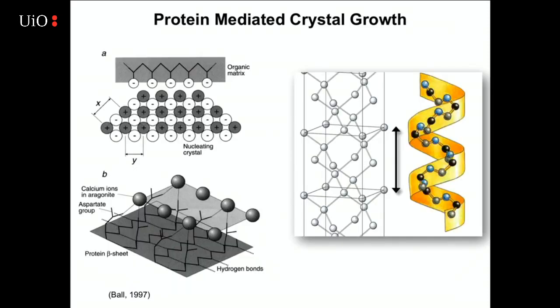So I talked about the abalone and how it had this amazing ability to grow materials based on the fact that they had protein. So these proteins are made out of those 20 amino acids that are on the back of your periodic table. And the way it works is that organisms in the ocean may have this organic matrix, this protein. In the case of the abalone, the one that actually grows this calcium carbonate-based material, are very negative charged amino acids. They have rows of aspartic acid or glutamic acid, and they can grab that calcium from the environment. They can put down calcium carbonate, and they can help with the nucleation of these materials, but they can also act as poisons to tie up certain crystallographic growth.